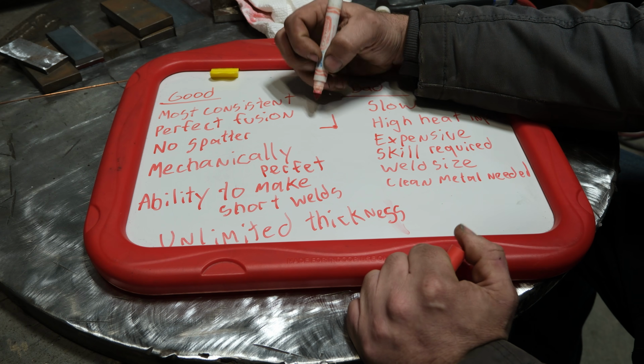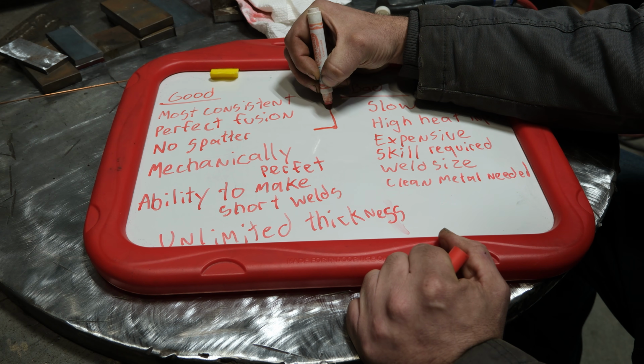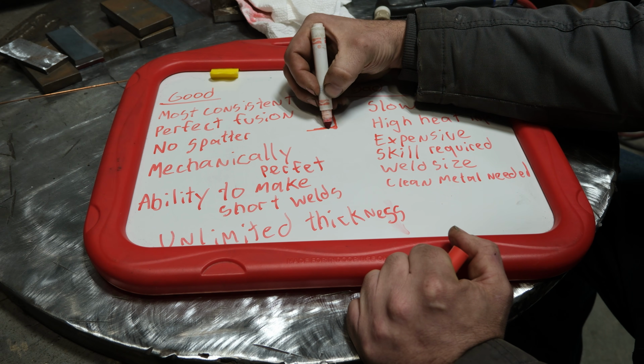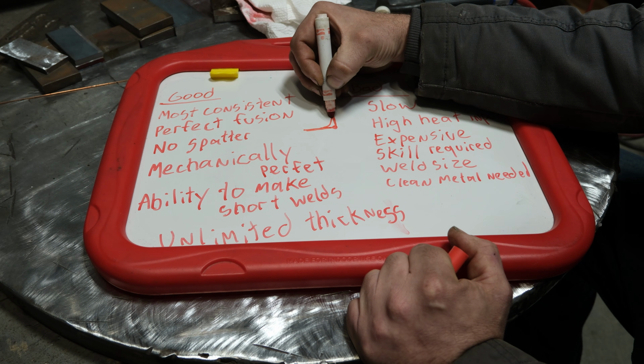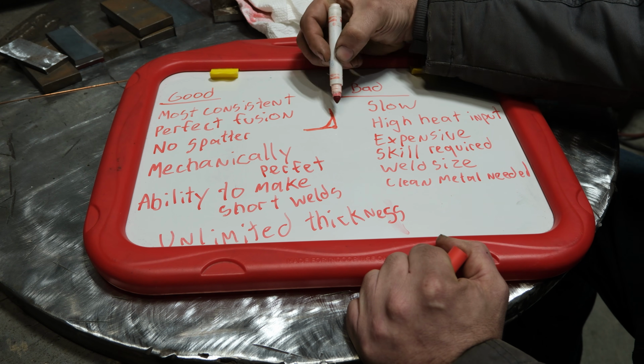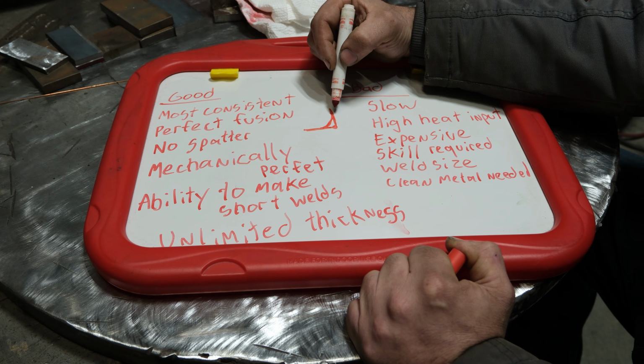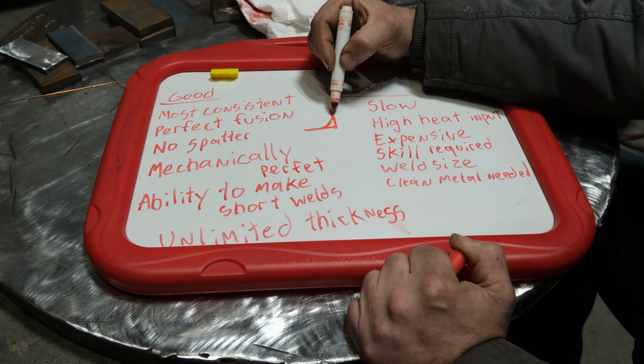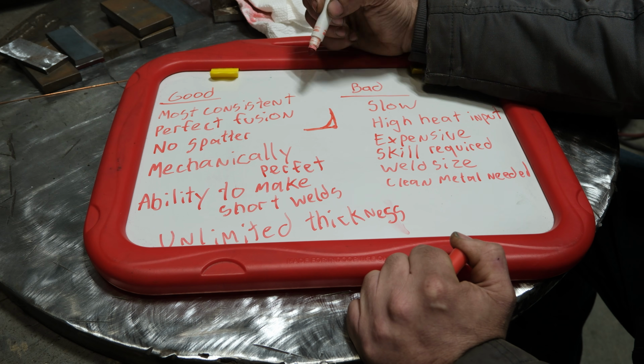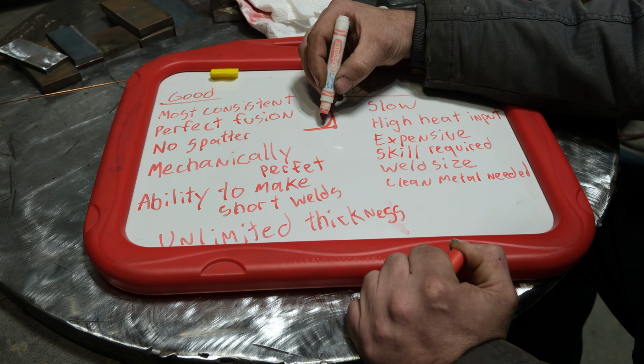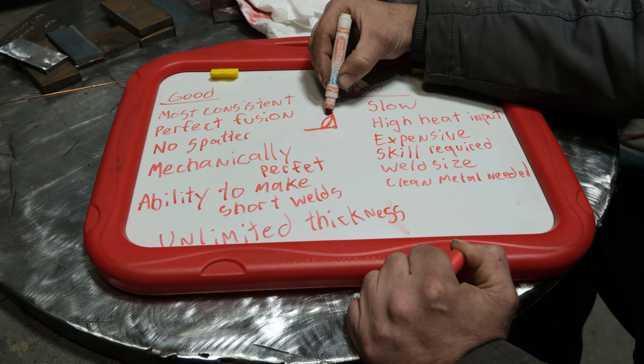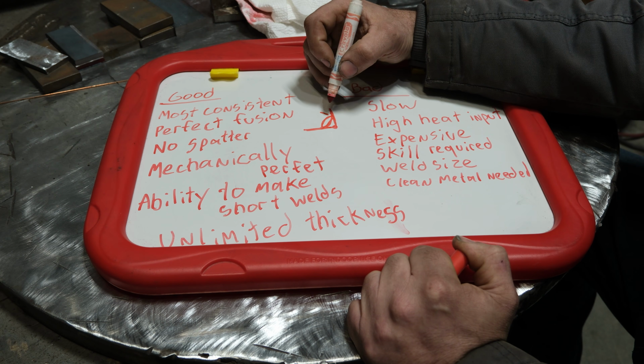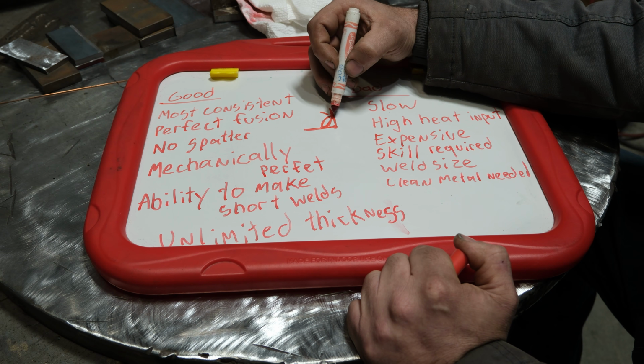Now, mechanically perfect, what I mean by that is depending on how the stress is applied to the weld, TIG welds typically are more or less concave, and having this profile can be extremely beneficial under tension because it doesn't give a hard spot for a crack or a tear to form. So when you look at your typical stick and your MIG welds, those tend to be more convex, and under stress it gives a great place for a crack or a tear to form. With TIG, it spreads the load more evenly, which can be a huge benefit.